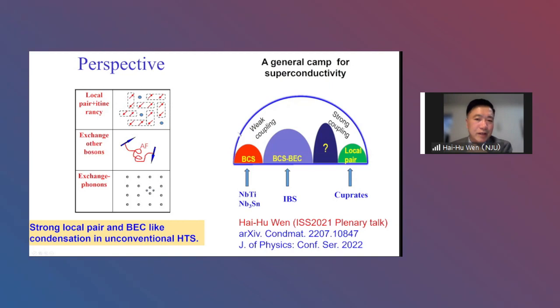So here I draw a general map for superconductivity. In this big camp, the BCS just sits in the corner, which is due to the so-called weak coupling picture, instability of the Fermi surface. However, in the cuprates, we have a local pair due to the strong correlation. In that case, we have some kind of finite density state, and gradually we have superconductivity. So the Tc is determined by the superfluid density. And probably the iron-based superconductors are in between, in this region, corresponding to the BCS to BEC crossover.